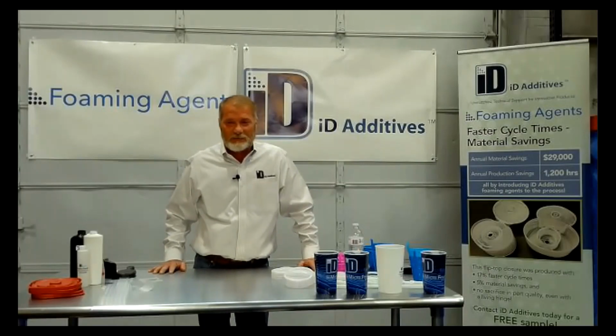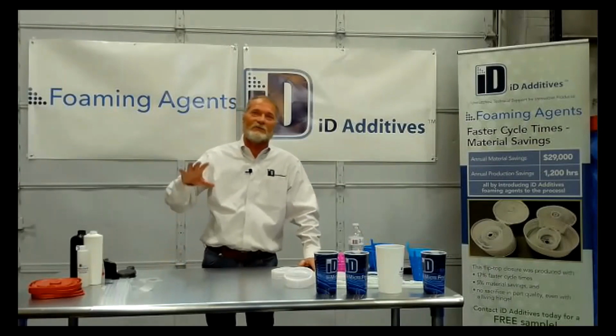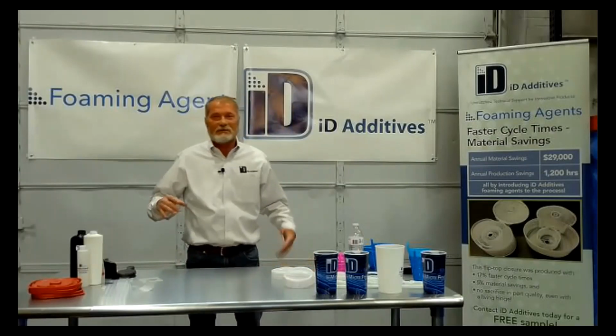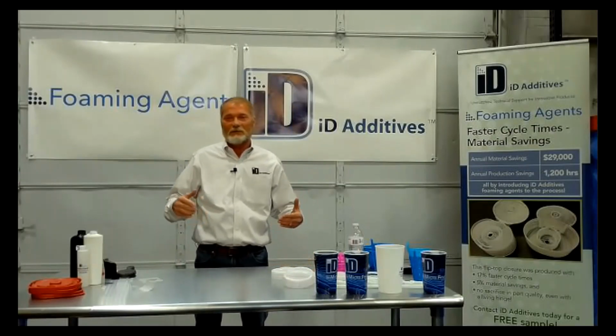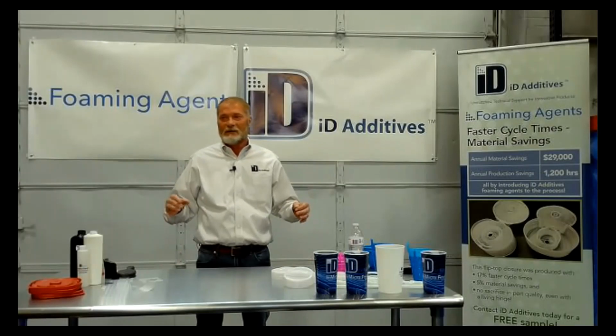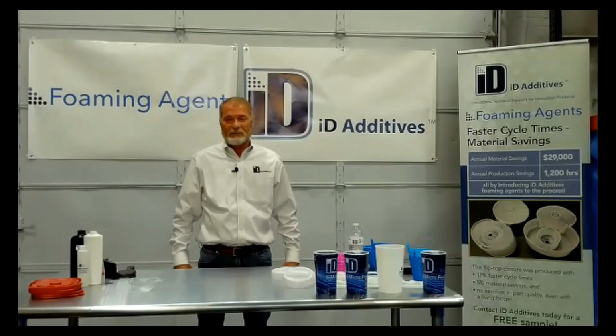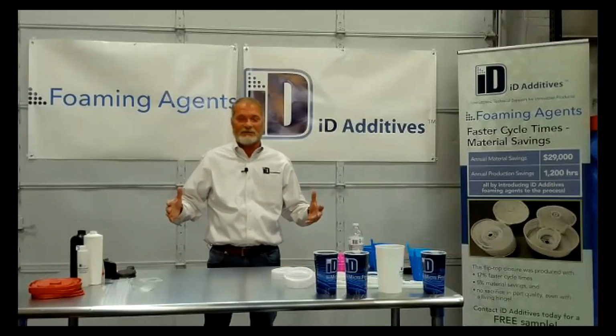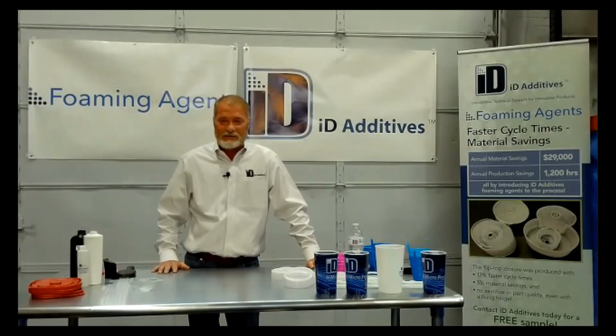And chemical foaming agent with nitrogen, or even straight chemical. I've had an opportunity where I foamed a real thick pallet. They were using nitrogen and 0.5% chemical, but there was so much mass in this pallet that the chemical really didn't help a whole lot. But it did a little, but not as much as I would have liked it to. So I said, all right, because they were really worried about that cycle, we're going to drop 2% chemical foam, shut the nitrogen off. We dropped 40 seconds out of the cycle and over a quarter pound of weight out of the part.